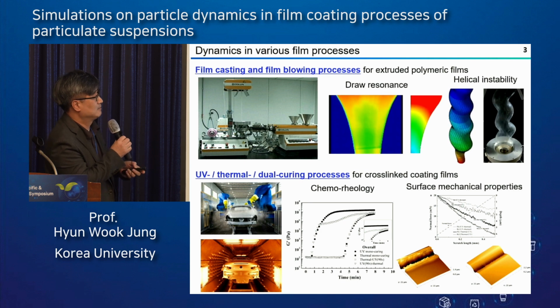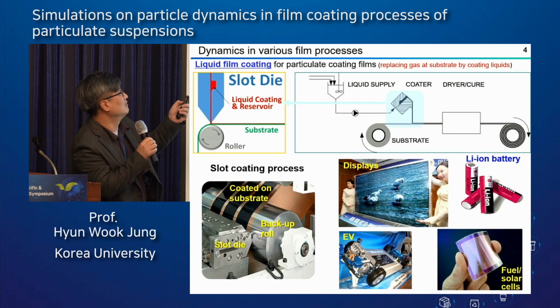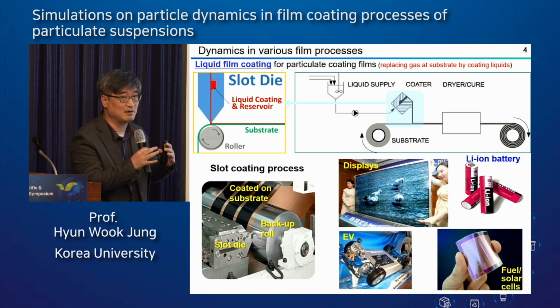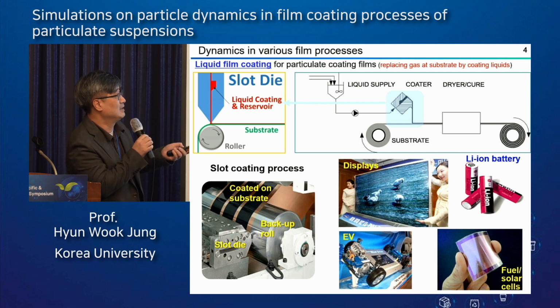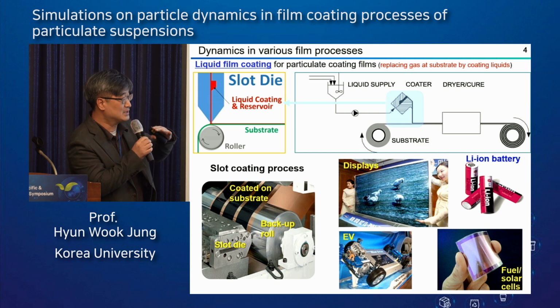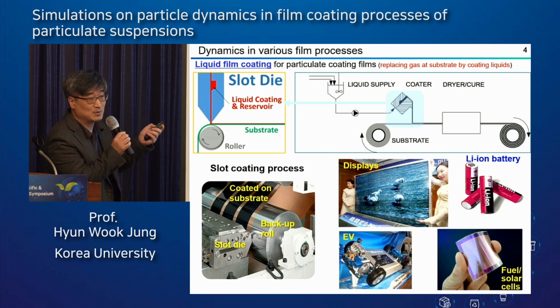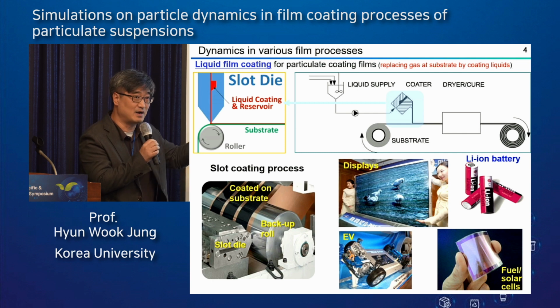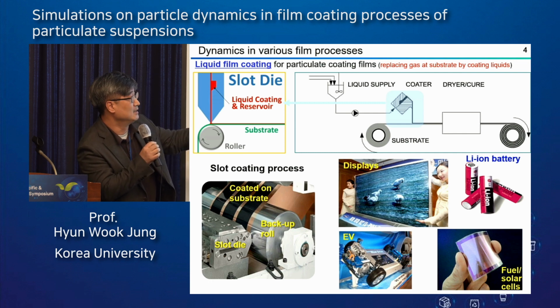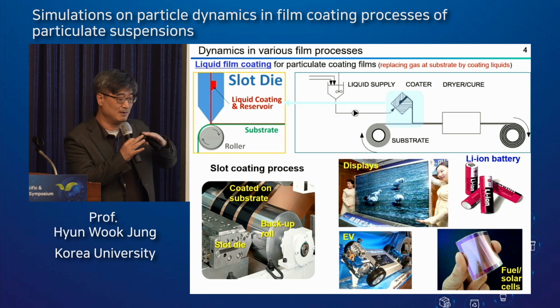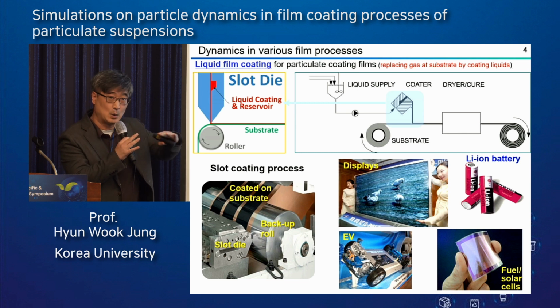And the third part is liquid film coating for making particulate suspension film onto a moving substrate. So this is the main process of this talk. Film coating is a replacement of gas at the moving substrate surface by the coating liquid. As shown in this simplified coating line, for example slot coating, the coating liquid fed from the feed will be distributed and metered inside the coater, then deposited on the moving web, and then dried and cured in the next, final step to make particulate coating films.